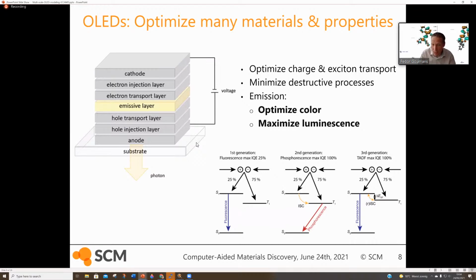And the second generation of OLED emitters were phosphorescent emitters. These would typically be transition metal complexes, so heavy elements where relativistic effects play a larger role. They would have relatively large intersystem crossing rates. And so when the exciton would internally convert to a singlet state, it could rapidly intersystem cross through the spin-orbit coupling to a triplet state, and that triplet state could then also, again through spin-orbit coupling, phosphoresce to the ground state. So in developing these type of materials, typically you're looking at optimizing the spin-orbit coupling between the singlet and the triplet manifold, as well as from the triplet excited state, typically the T1 state, onto the singlet ground state.